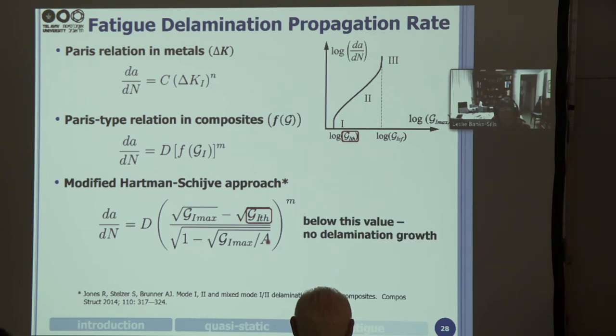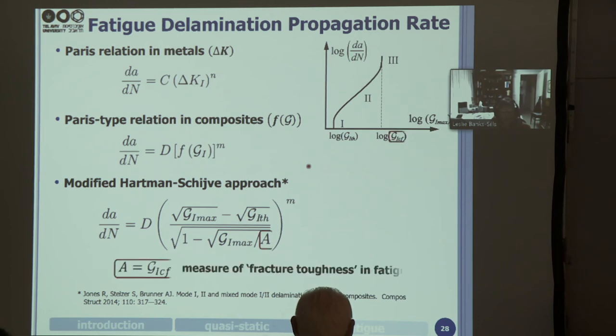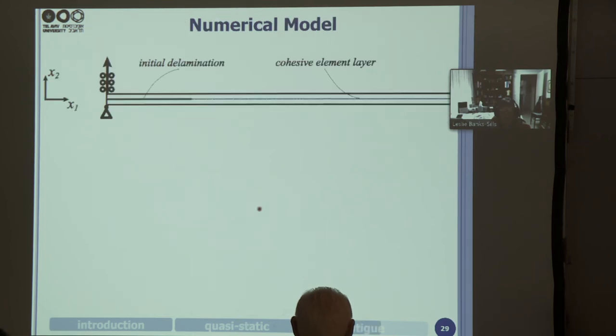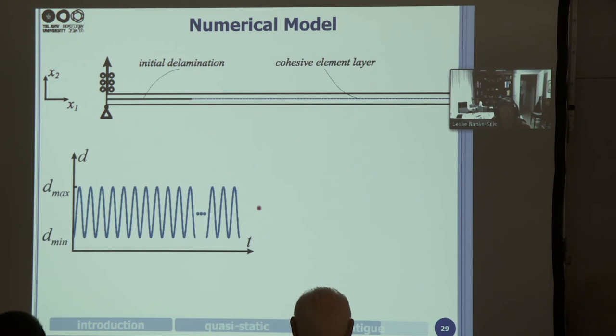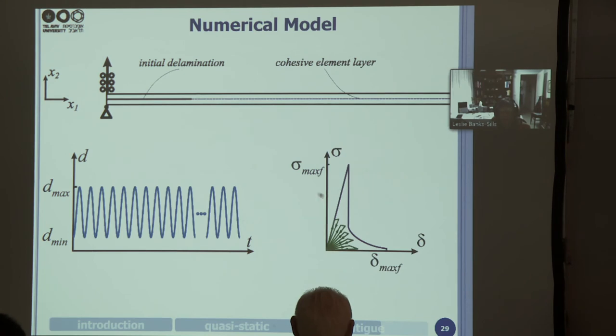G1 threshold is the value of G1 below which there'll be no delamination growth. And A is the cyclic fracture toughness, analogous to G1C. It's a measure of the fracture toughness in fatigue. It's not G1C. So we have to find A, and we do it from the data that we have obtained. We have to find A and G1 threshold. And I don't have time to go into the details, so I'm just going to show you the numerical model. For the tests that were carried out for 3 million cycles, we used the cohesive zone model to propagate the delamination in fatigue in the numerical analysis.